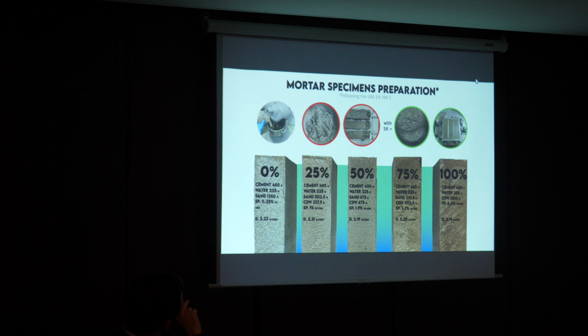And after that, we can see here the mix design used for each type of sample prepared, with the different rates of replacement of the standard sand, and the doses of super plasticizer, arriving, in the case where 100% of the sand was replaced, to 6% of super plasticizer by weight of cement. And we note there is also a high amount of super plasticizer.